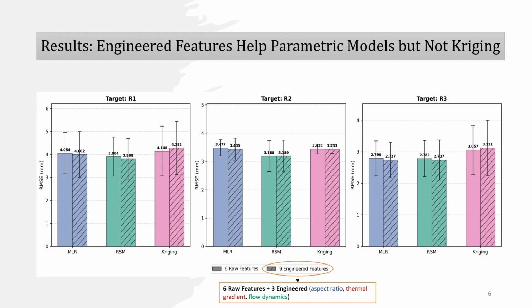Kriging behaves differently. When the engineered features are added, kriging does not improve and in some cases becomes worse. This suggests that the larger 9-dimensional input space is problematic for a distance-based method when the dataset has only 80 configurations.